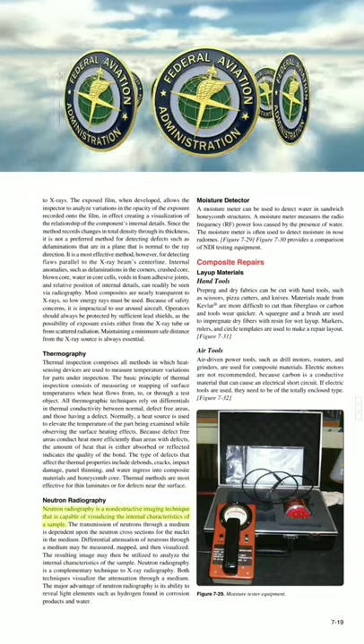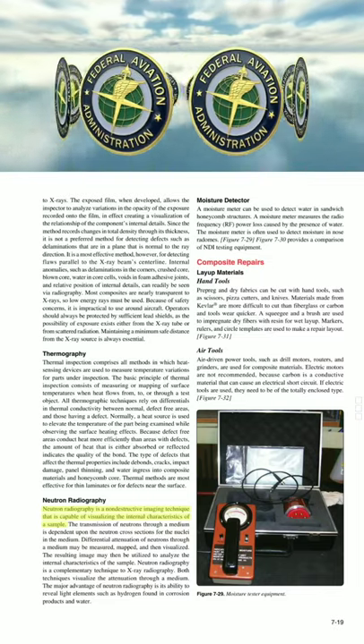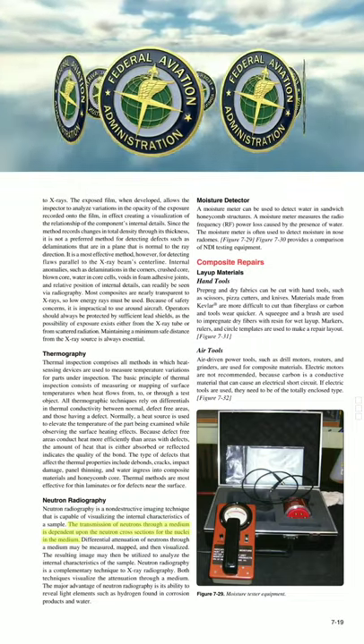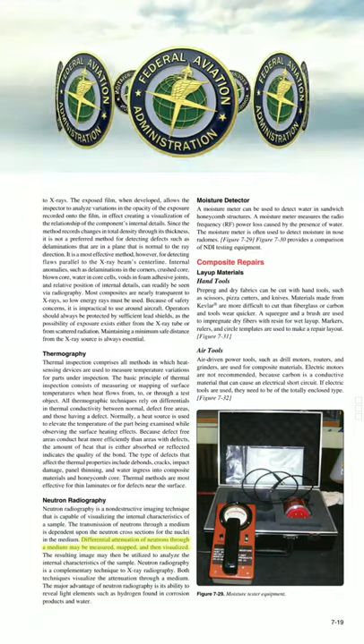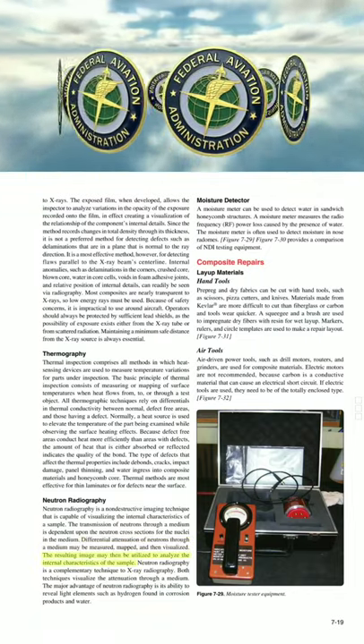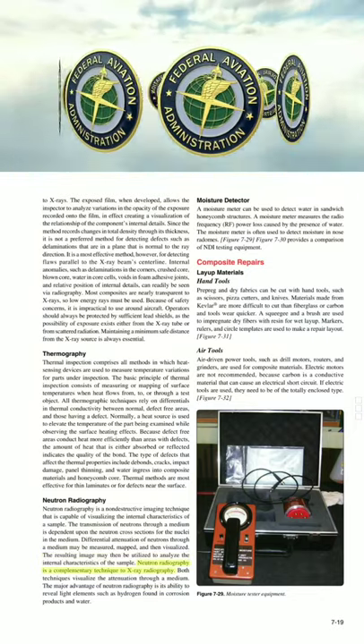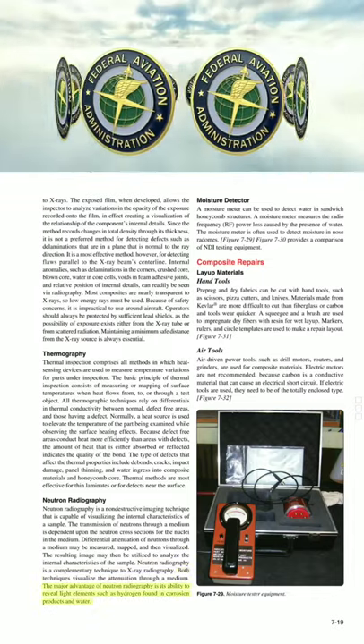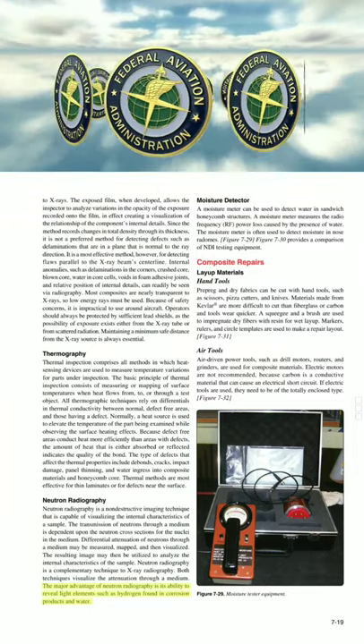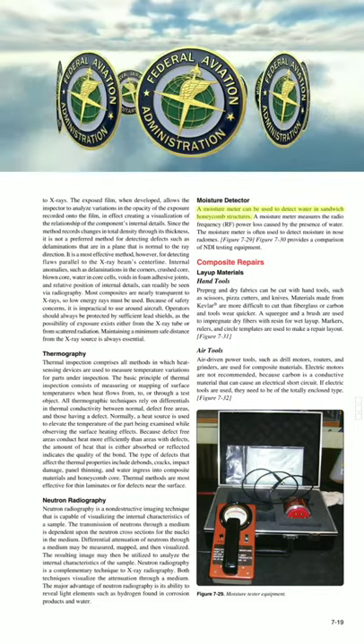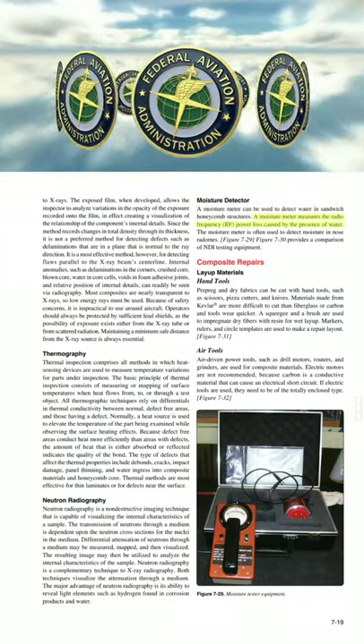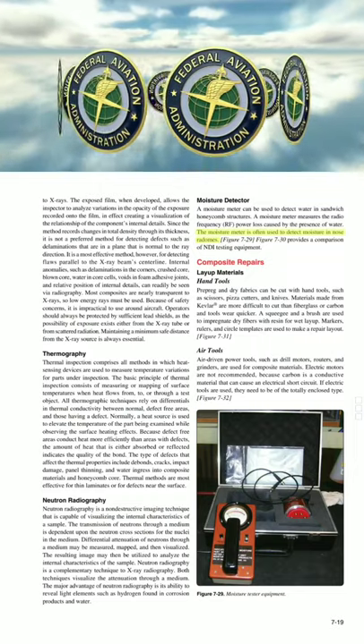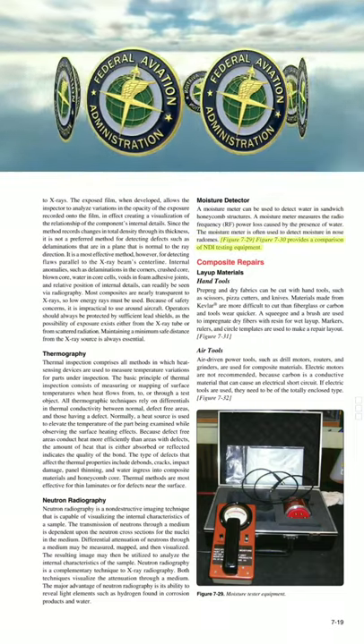Neutron radiography is a non-destructive imaging technique capable of visualizing the internal characteristics of a sample. The transmission of neutrons through a medium depends upon neutron cross-sections for the nuclei in the medium. Differential attenuation of neutrons may be measured, mapped, and visualized to analyze internal characteristics. Neutron radiography is complementary to X-ray radiography; the major advantage is its ability to reveal light elements such as hydrogen found in corrosion products and water. A moisture meter can also be used to detect water in sandwich honeycomb structures by measuring radio frequency (RF) power loss caused by the presence of water, and is often used to detect moisture in radomes.